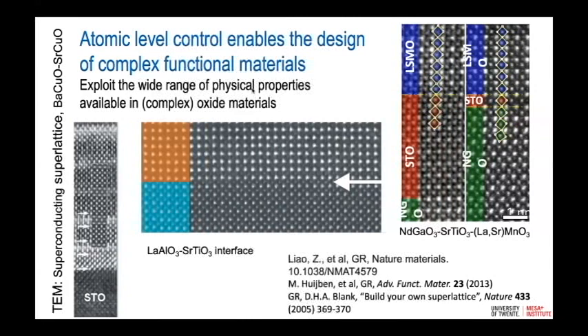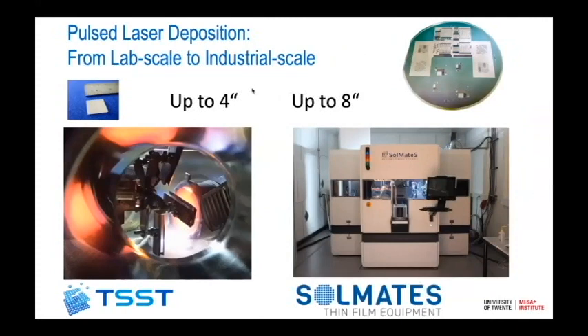In the last few decades or so, we tried to push this pulsed laser deposition technology in such a way that we are able to control the materials on an atomic scale. But more important is that in the last few years or so, together with two spin-off companies, Twente Solid State Technology, TSST, and Solmates, we also worked on scaling up these pulsed laser deposition tools to larger areas.